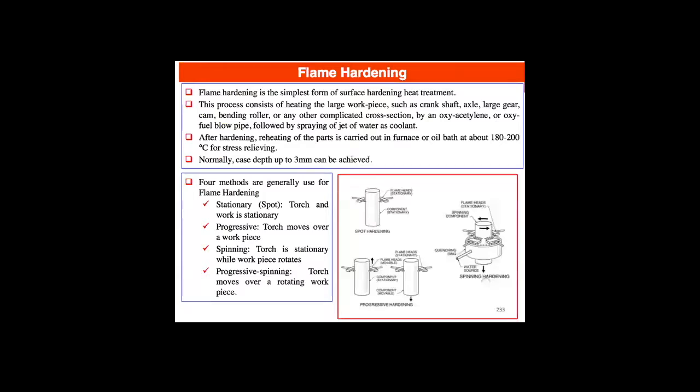But basically, all you're doing here is you're taking a torch, you're heating up the surface, and then rapidly quenching. So you're just hardening the surface of your sample, right? And by doing this, the depth to which it's hardened is called your case depth, right? So that's how thick your hardened layer is on the surface of your material versus your tougher steel, right? And it's just a matter of how deep your heat went, right? How big of a temperature gradient, right?